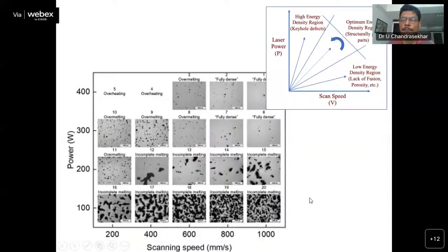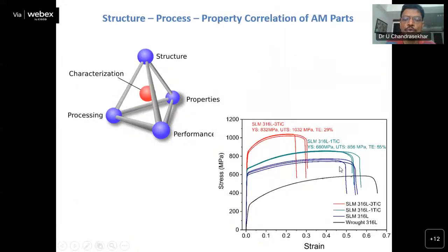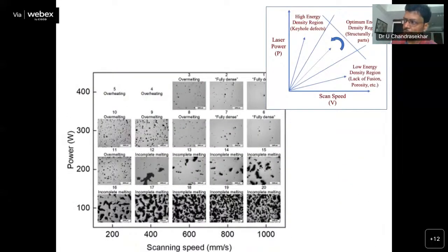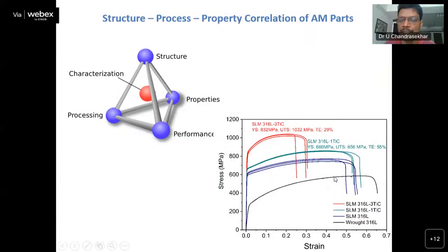So to make the parts with the necessary strength and to put them into service, there are a lot of optimization procedures which are put into play. One of the primary examples is considering the volumetric energy density, wherein you derive the density as a function of the laser speed, laser power, hatch spacing, and layer thickness. Try to find out which is that process space, process window, wherein you are likely to encounter keyholing, or if you put less energy, most of the particles remain unfused. So you need to find out the optimal mix of these parameters leading to volumetric energy that is just sufficient enough to melt the part and create a track with the necessary geometrical integrity.